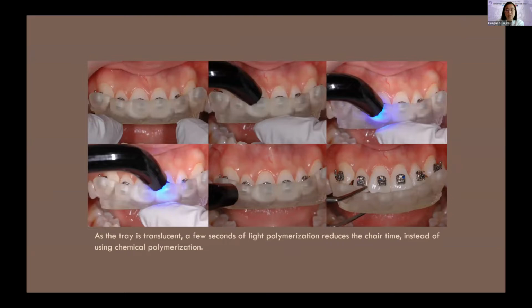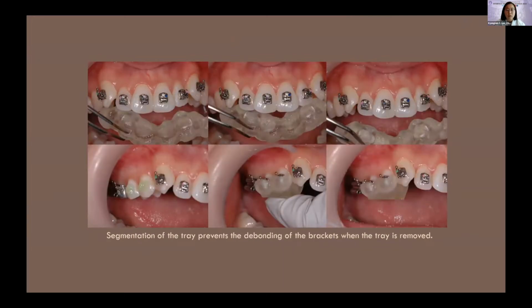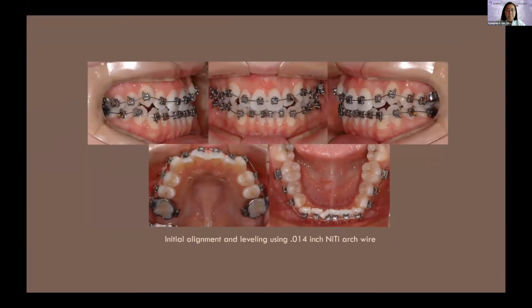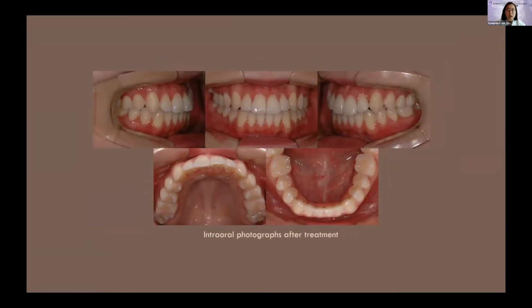As the tray is translucent, a few seconds of light polymerization reduces the chair time compared to the time required when chemical polymerization is used. We cut the tray into 3 parts to prevent any debonding of the brackets when the tray was removed. After indirect bonding, a .014-inch nickel titanium archwire was placed for initial alignment and leveling. After 1 year and 3 months, the orthodontic treatment was completed. During the treatment, repositioning of brackets was not performed.